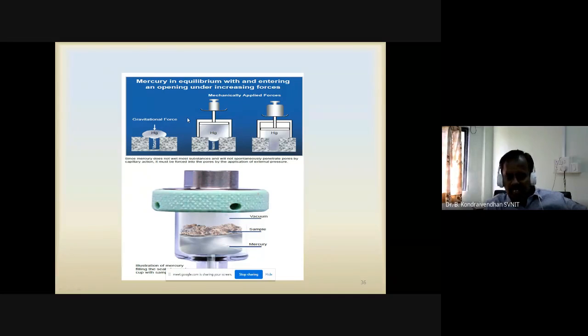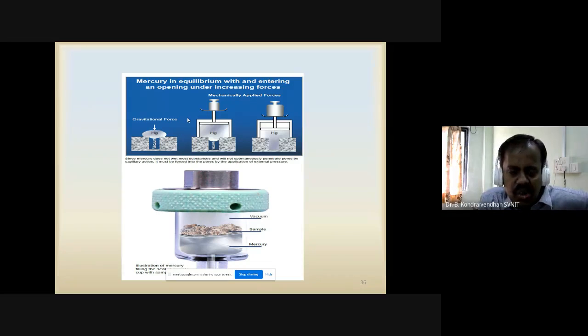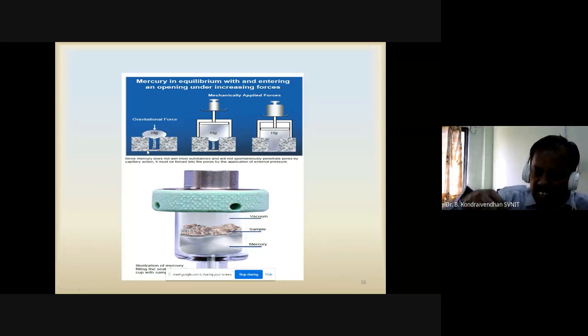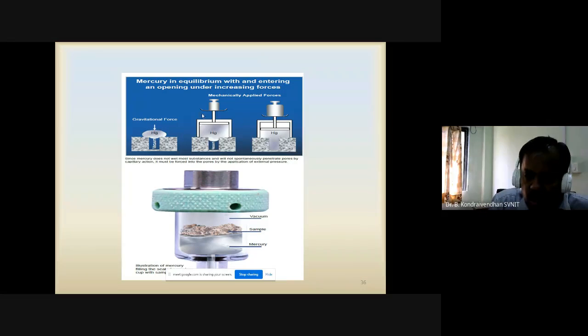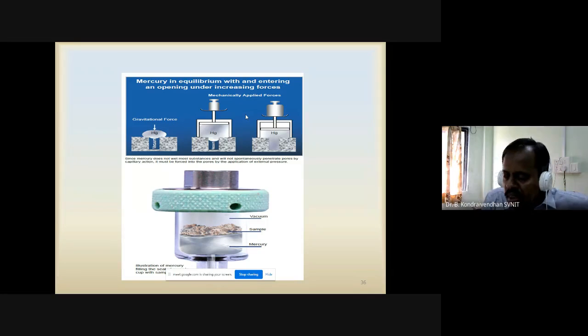Here it is better explained how the mercury is penetrating inside. You can see first we are creating the vacuum, then we are applying external pressure, that is 60,000 psi. At that time the mercury is entering inside, where the vacuum was removed. That's how the mercury is going inside the voids. That's how we are measuring the porosity and pore sizes. Actually the software will give you directly the porosity and pore sizes. Okay, so this is how it is performed.